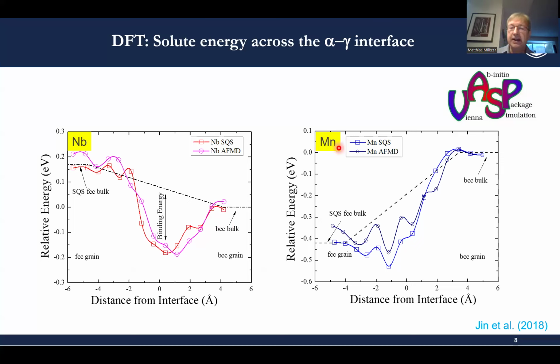Manganese, on the other hand, is an austenite stabilizer, so it's the other way around. FCC has the lower energy level compared to BCC, and we also have a little bit of a potential drop here at the interface, not as pronounced as for niobium, though. Now, the question is, what do we do with these sort of data that we have?